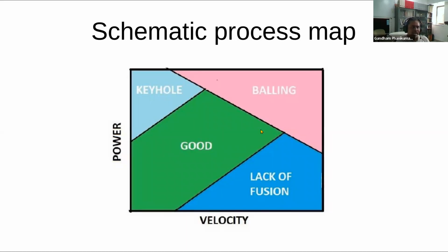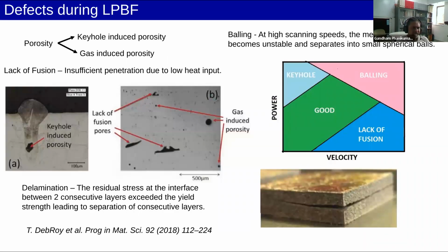And basically, you have to distinguish between these two types and play in between to get a good deposit. And of course, balling is another defect, which is also possible when your power is high, but you don't have enough time to allow the melt to sink and deposit at the bottom of the powder bed, so that it can lead to cohesion with the rest of the solid. So there's a nice review by a welding expert, DebRoy, on these aspects, because quite a bit of our understanding is coming from welding only. So you could look at that review.